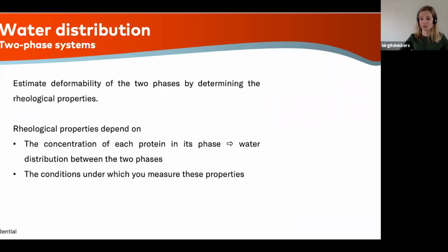And that's then the second point that I wanted to show you a bit more about today: how to measure rheological properties and how to use rheology as a tool to predict structure formation in shear cell technology, but also maybe later on in extrusion. You can only measure these types of viscosities under relevant conditions, because if you measure rheology at room temperature and in the end your process is at elevated temperatures, above 100 degrees, then the viscosity at room temperature doesn't really say you anything.